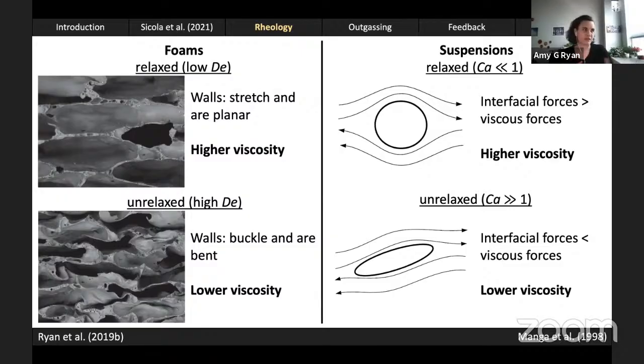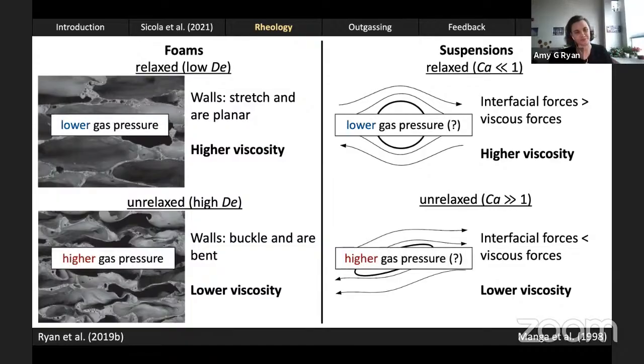Now, I spent a portion of this talk trying to convince you that bubble pore pressure matters for viscosity. What I've actually found is that it doesn't hold up in these particular deformation regimes. The materials deformed at low Deborah number are actually the ones that have lower gas pressure and yet higher measured viscosities. And the inverse is true for the unrelaxed materials. I would posit that the same might be true for suspensions, but I'm happy to discuss that if you disagree in the discussion period.